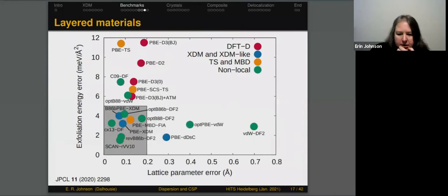A well-known problem that has come up in recent years for DFT dispersion corrections is layered materials. Here we're looking at exfoliation energy again, the energy to pull apart layers, but now on a set comprised mostly of transition metal dichalcogenides, things like molybdenum disulfide. Here, again, we tend to get overly large dispersion coefficients for the metal atoms and also for the chalcogen atoms within these TMDCs if one uses a